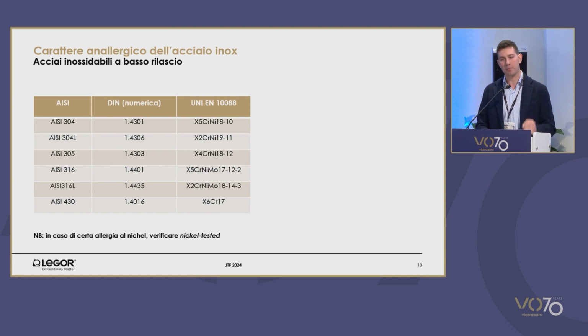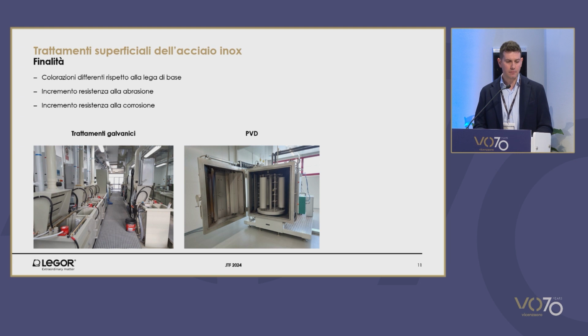Stainless steel alloys, as listed here in this slide, can be considered as hypoallergenic because the nickel release is compatible with the regulations. And we've been referring to the regulation, to the alloy as such. At times, this alloy is not enough. Additional treatment is added on the surface to modify the properties, for example, the aesthetic properties, to change the color of the jewel or the fashion accessory, or to improve corrosion resistance. In the case of the fashion industry and jewelry, superficial treatment should exclude paints, especially so in the watches, because the outlook can be worsened.